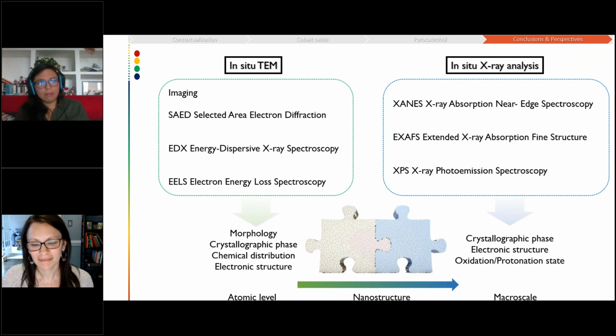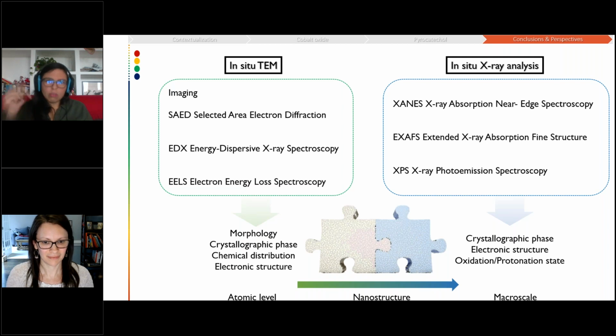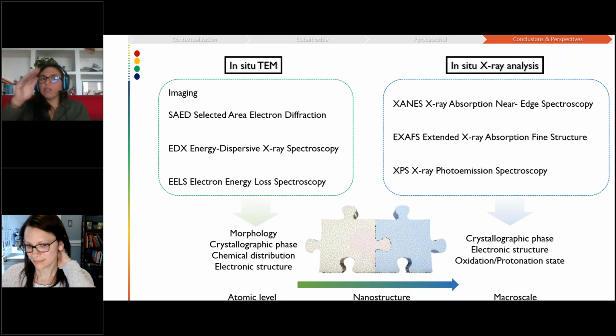Because I think we observe that when we cycle for a long time, the potential starts to shift towards lower potential, meaning that the overpotential is decreasing. And at the time, I was thinking, wow, we are improving the electrocatalytic activity, and then I understood that it is due to the ferricyanide. So when you don't put it in, the electrocatalytic activity keeps stable, and it does have an impact on the electrocatalytic activity if you cycle for a long time.